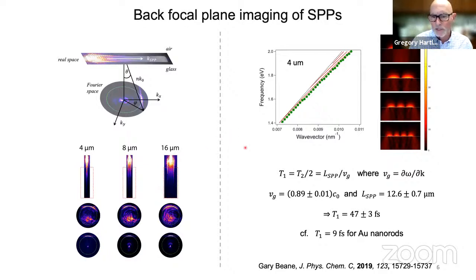Okay, so what we do is we do this experiment. We measure the wave vector for a bunch of frequencies, and then we plot that as frequency versus wave vector to generate a dispersion curve. And so the lifetime of the plasmon is given as the propagation length divided by the group velocity. And the group velocity is just the slope of that dispersion curve. So you see we need both the propagation length and the wave vector information to get the lifetime, right? So we measure a bunch of frequencies to get this speed.